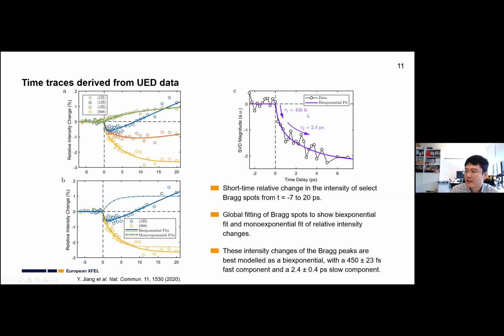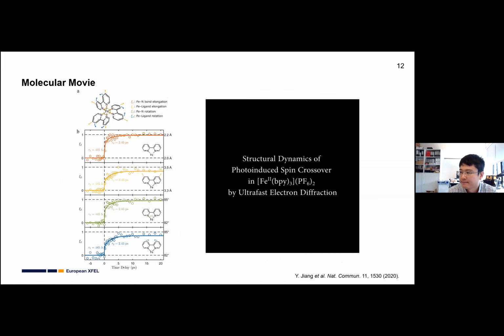And we assigned the first ultrafast part to iron-nitrogen bond elongation coupled with the ligand motion. And the 2.4 picosecond part is the molecular reorganization, relaxing down to the bottom of the high spin state.